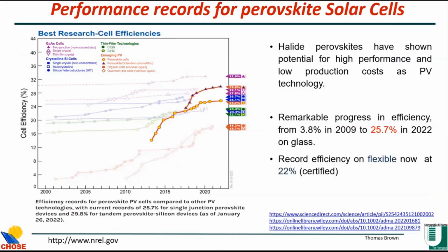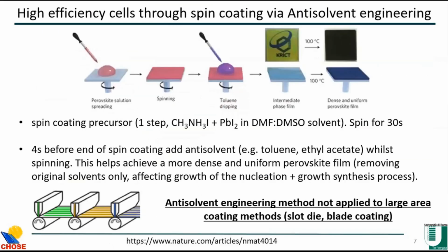Perovskite solar cells, since 2009, where the initial efficiencies were 3.8%. Now the record is 25.7% at standard test conditions. And flexible solar cells started a bit later, but they've also reached very high efficiencies, which are now 22%. And the key, as I was saying, is the crystallization and the conversion from precursor to the final perovskite layer. And most high efficiency cells use what is called anti-solvent engineering.